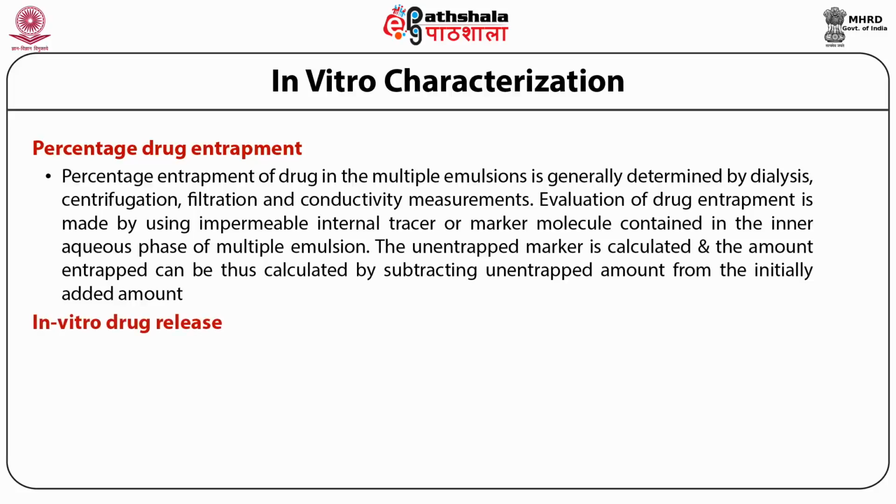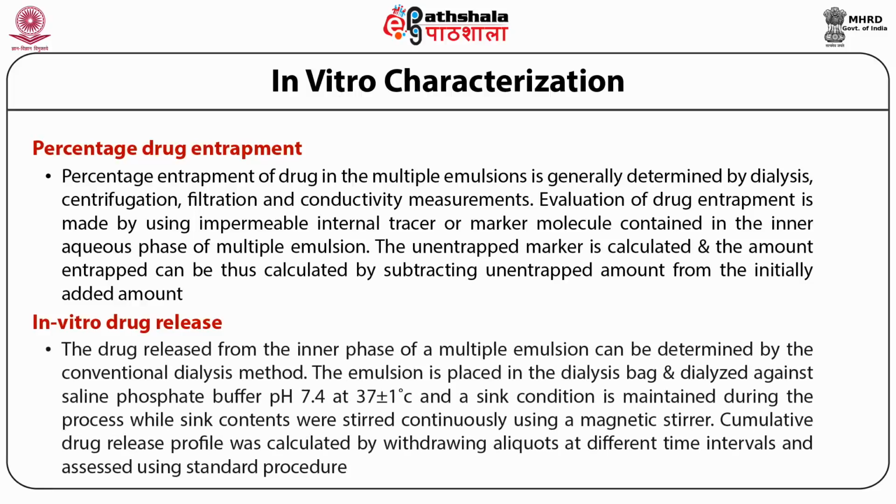This is again a very important parameter to decide what is the release pattern, whether the multiple emulsion is sustained release or immediate release. The drug release from inner phase of a multiple emulsion can be determined by conventional dialysis method. The emulsion is placed in the dialysis bag and dialyzed against the phosphate buffer saline pH 7.4 at 37 plus minus 1 degree centigrade, and a sink condition is maintained during the process while contents were stirred continuously